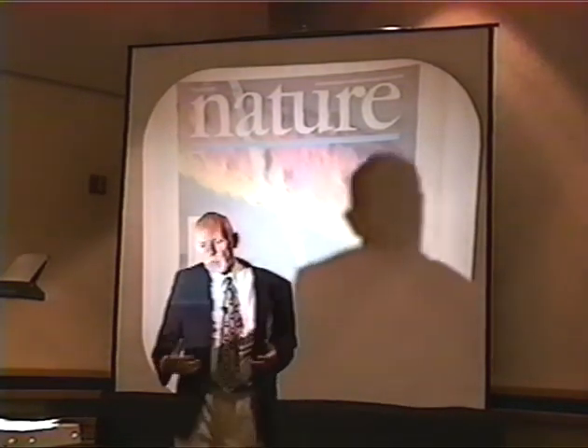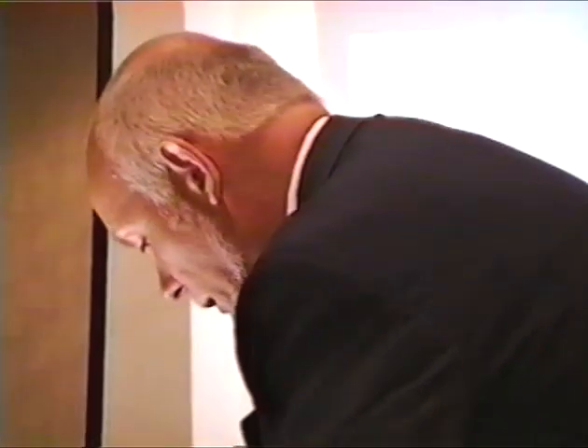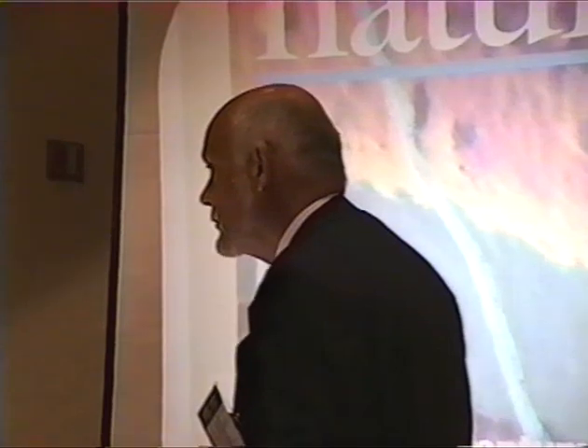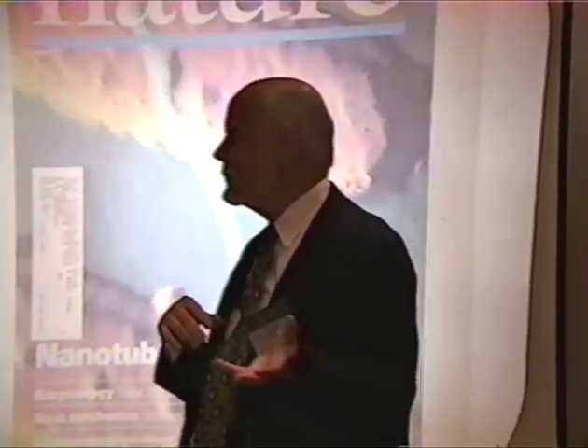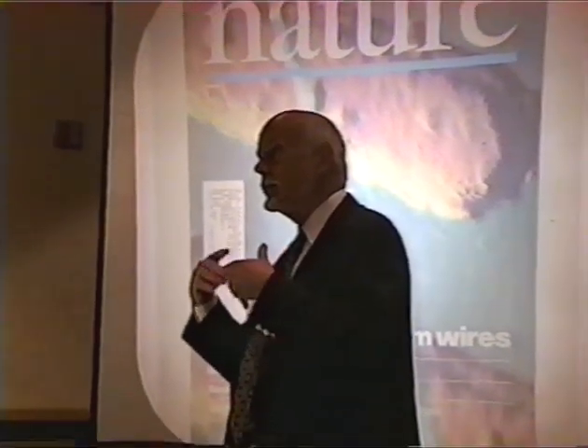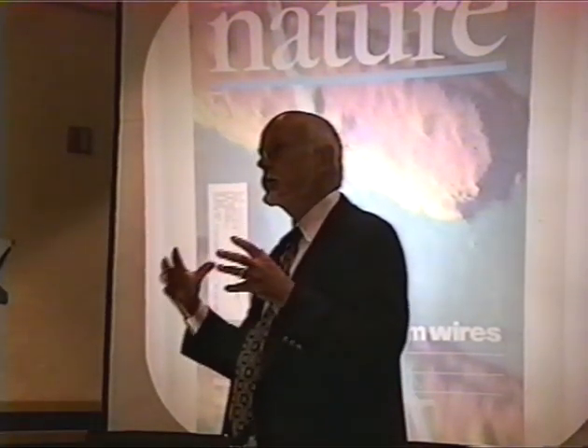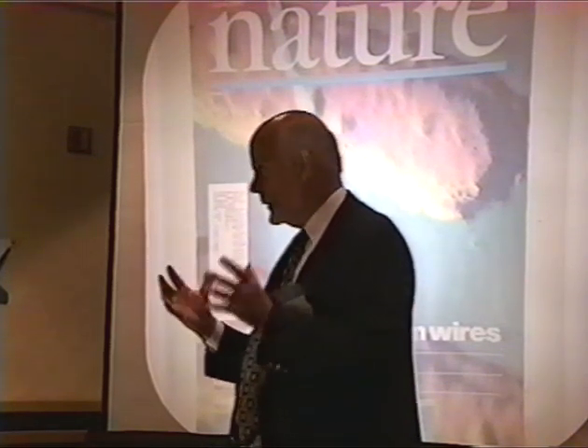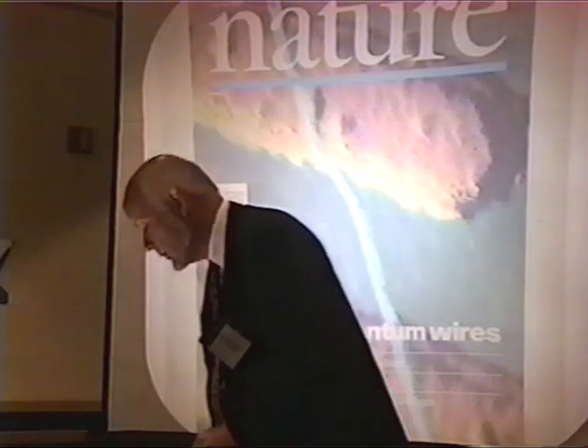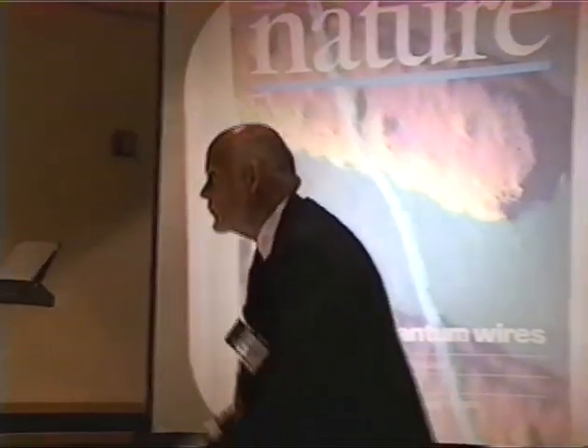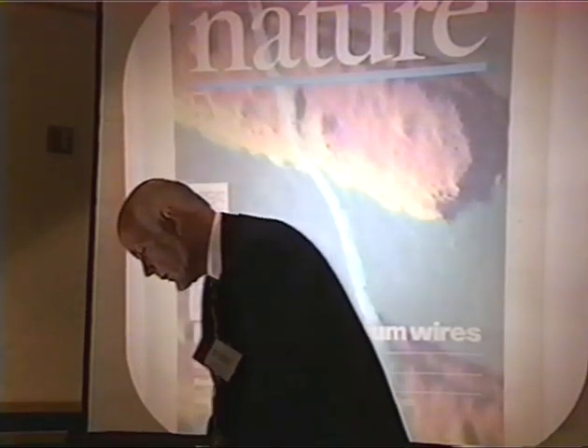So one of the intriguing aspects about this is we appear to have the answer of how to make a molecular wire. Make it just simply out of carbon. If you pick one of these armchair tubes, it's guaranteed to be metallic. And it appears to be metallic all the way down to, in this case, millikelvin temperatures. What happened to the Peierls instability of one-dimensional wires? Well, we're not quite sure, but we think it may have just up and gone away because this tube has such tremendous structural rigidity to it that the energy cost of making a distortion that would open up a gap is greater than the energy advantage you would make by stabilizing a bit the otherwise conduction electrons.